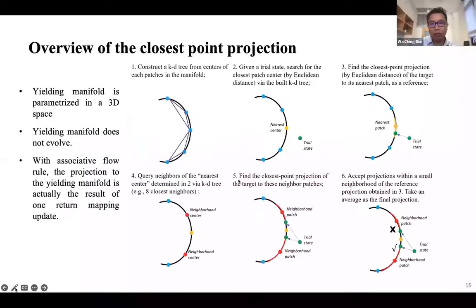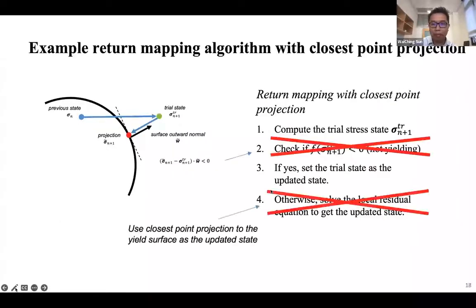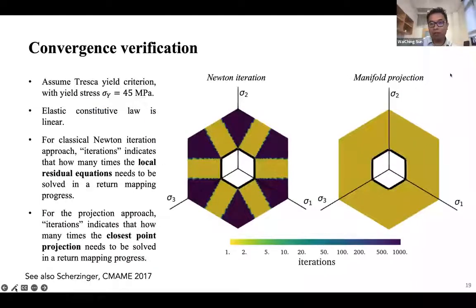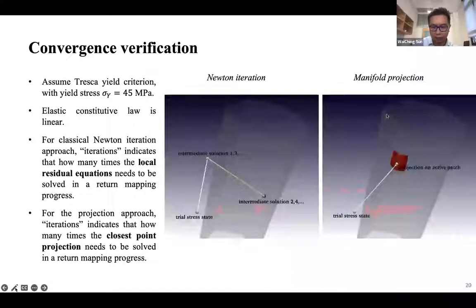But in the new approach, because we can conduct the local projection between the local patch and the trial state, but not through the entire global yield surface, we can bypass this problem by having the manifold projection directly onto the individual patch.